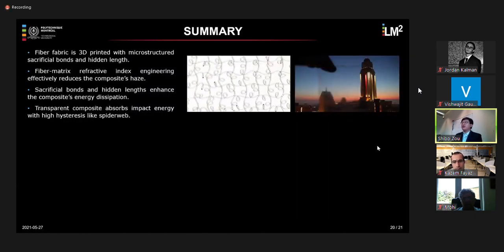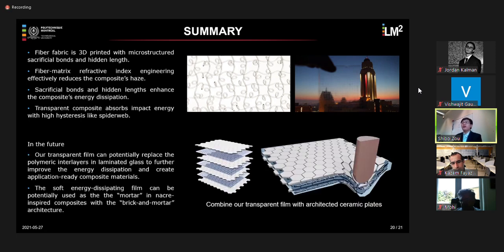To summarize, in this project, we were able to implement the sacrificial bond toughening mechanism into engineered materials and achieve this high energy dissipation behavior, which is similar to the energy dissipation behavior in spider web. What will be interesting to do next is to integrate this impact absorbing film in laminated glasses or other laminated plates to improve the energy dissipation of engineering structures. Another interesting direction is to integrate our impact absorbing composite with the currently developed nature-inspired architectured ceramic plates, to use as an interlayer between those plates to further increase the energy dissipation behavior.